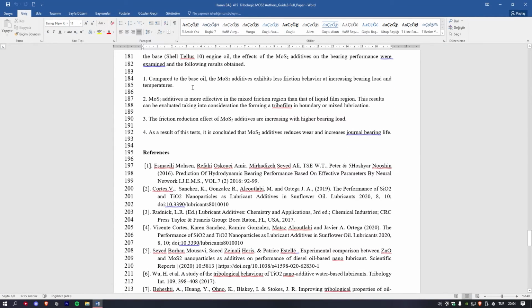1. Compared to the base oil, the molybdenum disulfide additives exhibit less frictional behavior at increasing bearing load and temperatures. 2. Molybdenum disulfide additives are more effective in the mixed friction region than in the liquid film region. These results can be evaluated taking into consideration the forming of tribofilm in boundary or mixed lubrication. 3. The friction reduction effects of molybdenum disulfide additives increase with higher bearing loads. 4. As a result of these tests, it is concluded that molybdenum disulfide additives reduce wear and increase journal bearing life.